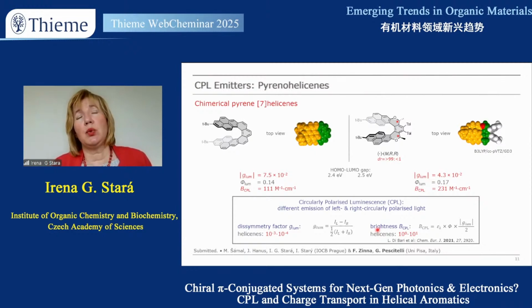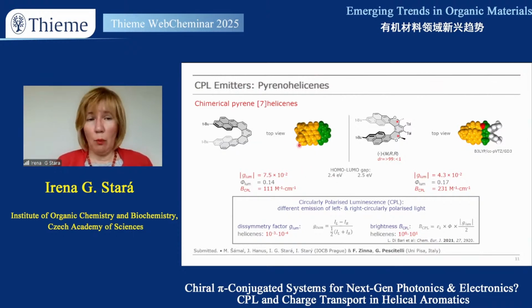Some authors recommend introducing the so-called CPL brightness, which has these two components, meaning that the total photon count is taken into consideration. For helicenes, you can see the usual range for CPL brightness, and what we found out for these two molecules. For this molecule, you can see that g_lum is a really high value, highly above the usually observed values, because it is 7.5 times 10 to the minus 2. Even for this compound, g_lum is very high. Ladies and gentlemen, I would also like to draw your attention to CPL brightness. In both cases, it is unusually high.